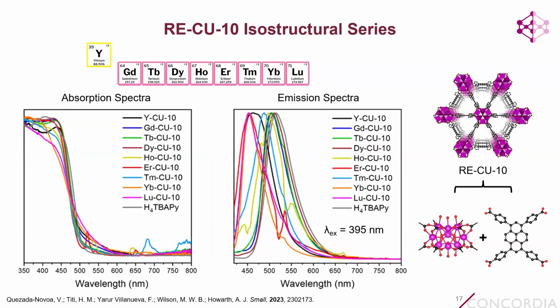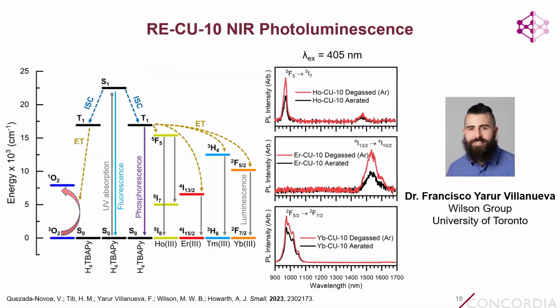We take a look at the ground state photophysics. We see that the absorption spectra shows primarily pi to pi star based absorption. So it's dominated by pyrene photophysics. And the emission spectra also is dominated by pyrene photophysics, where we see a mixture of monomer and excimer based emission. Now, to understand if that linker to metal energy transfer was actually taking place in these MOFs, the ones where it's theoretically possible to occur, we needed to collect some near-IR photoluminescence data.